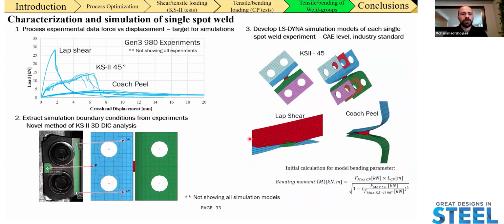In terms of the modeling response, we calibrated our models from the experimental force displacement data points, and that was the target for our simulations. We developed LS-DYNA simulation models for each of the single spot weld characterization techniques. We're not showing all of them, but these are representative models for the KS2, lap shear, and coach peel test. The boundary conditions were all extracted from the tests.